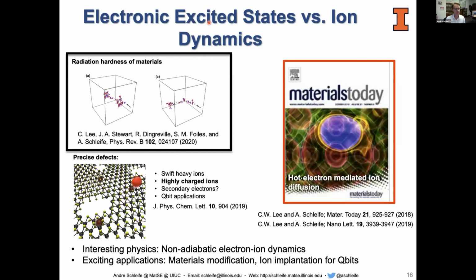If you have a piece of, in this case, silicon, and you expose that to energetic ion beams, which is of course what people do in the lab to understand the material properties, the material will experience defect creation, and any excited electron states that affect the creation of these defects will be important for this material. I will not discuss this example here in detail.